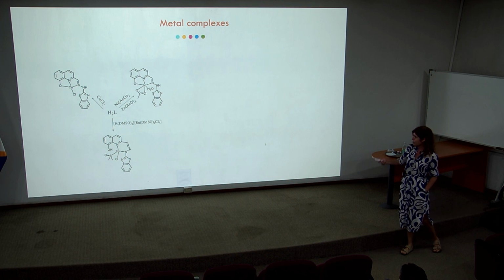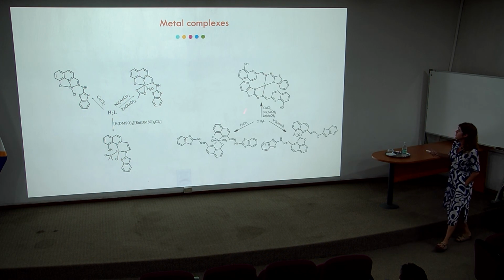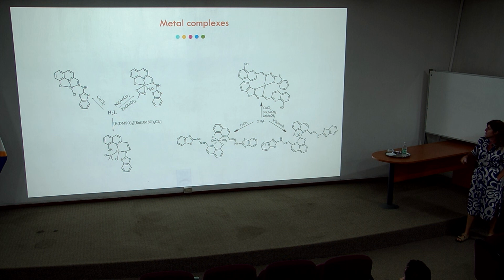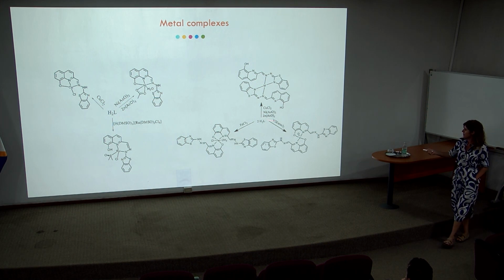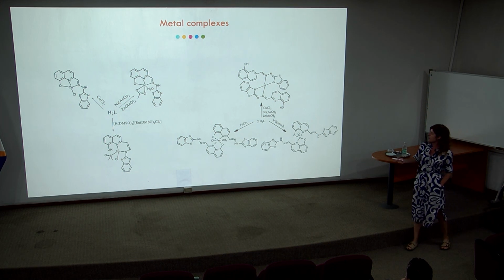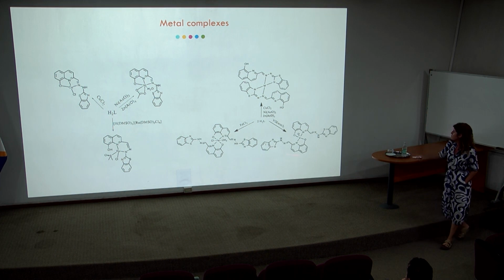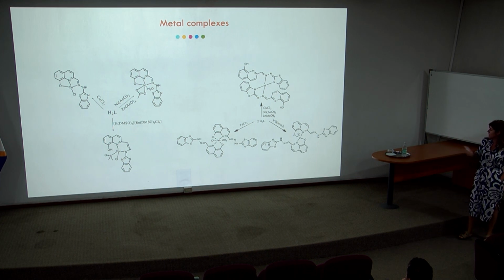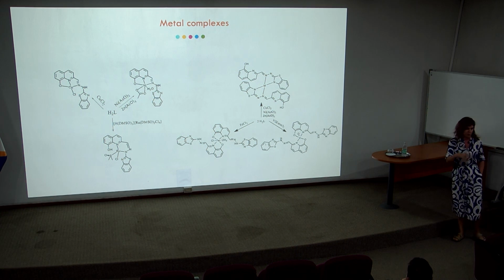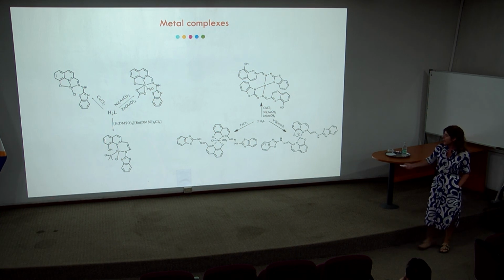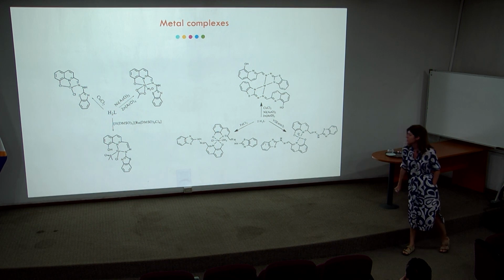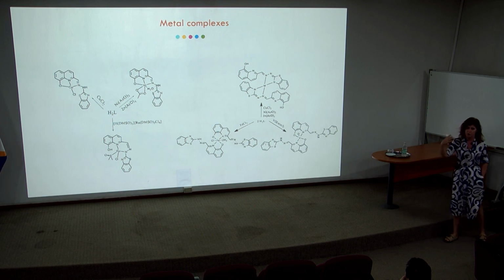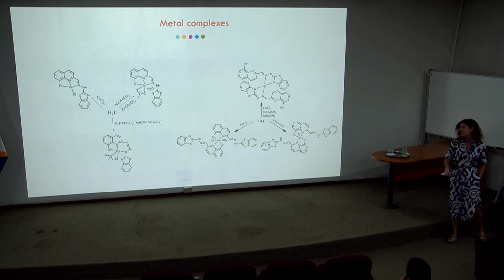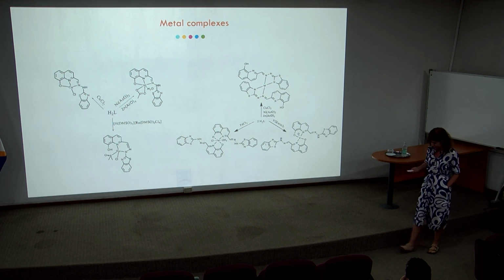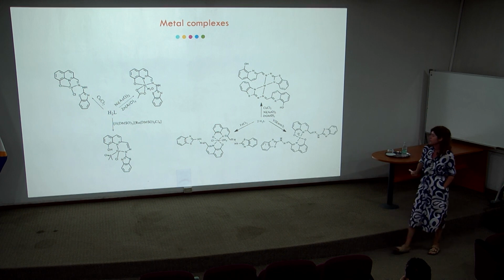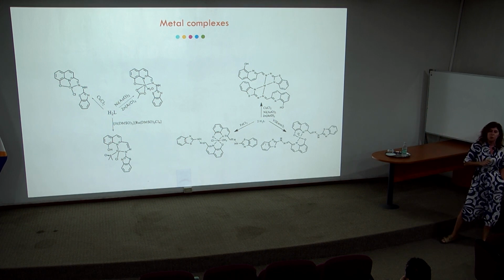We obtained 1-to-1 and 1-to-2 metal-to-ligand complexes in the case of copper, nickel, and zinc. With some metal ions, we only obtained the 1-to-2 complexes, as with iron-3 and vanadium-4, regardless of the metal ratio that we used in the beginning. And for ruthenium, it was interesting because we started with a ruthenium-3 species, which was reduced, we believe by triethylamine in the reaction system, and we obtained a ruthenium-2 compound.